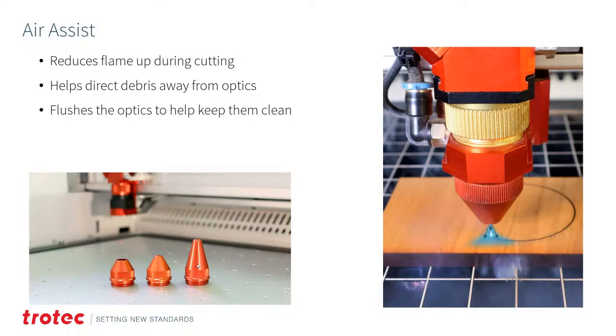And so air assist is ideal because it blasts a blast of air right down while you're cutting. It helps direct debris away from the optics, and it keeps those optics clean during that cutting and engraving process. If you have a flare up and you don't have air assist or a nozzle on, that flame can hit your lens. It can not only reduce the amount of laser power that you're getting when you're cutting or engraving, but it can also damage or destroy your optic. So you need to be very careful.